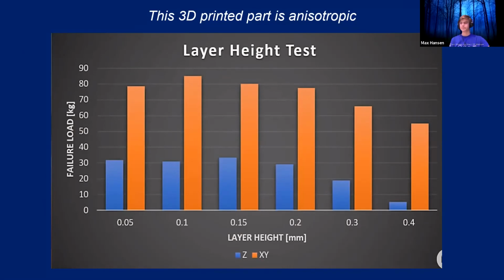A good analogy here is wood. If you have a 2x4 cantilever, it's quite strong because you would have to break it along the axis of the fibers. Whereas if it was built up with end grain, it usually breaks fairly easily, because just like the bond between the filament layers, the bond between the cells isn't that good in that dimension.